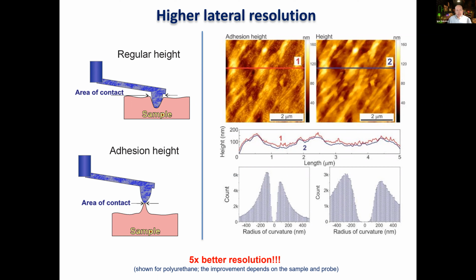In our method, we really do not need that. We can actually look at each individual tap, and each tap depends very weakly on the actual force. For example, adhesion does depend on force, but pretty weakly. It's simply a viscoelastic or time-dependent second-order effect. If you have a completely elastic material, it should not even depend on the load force.